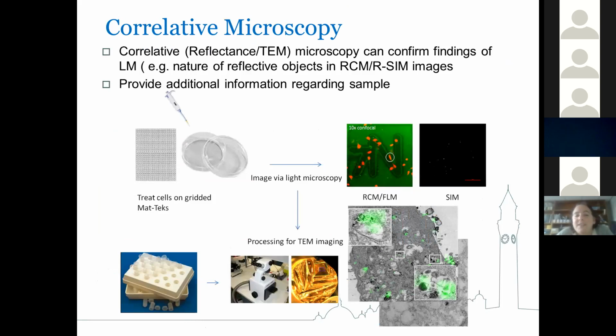Then we went on to see, could we actually correlate on the same sample and get the same cell and overlay the image we get from the TEM with the image we get from the reflectance confocal microscopy or from the SIM. So anyone who's worked with TEM will know that TEM is performed under vacuum, so you have to dehydrate the sample. So it's usually put in increasing amounts of ethanol to dehydrate it, and then it's fixed into an epoxy resin, and then with a diamond knife you slice your samples.